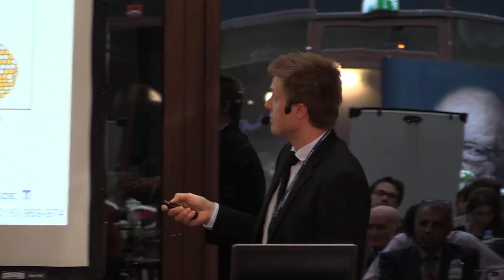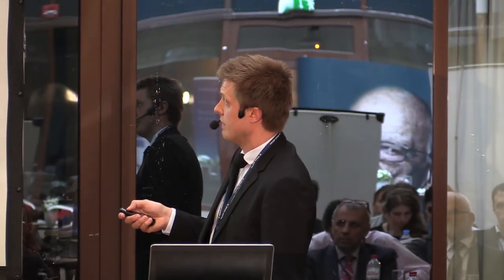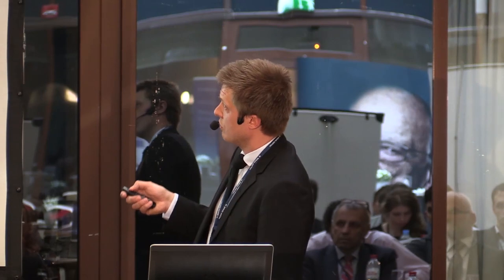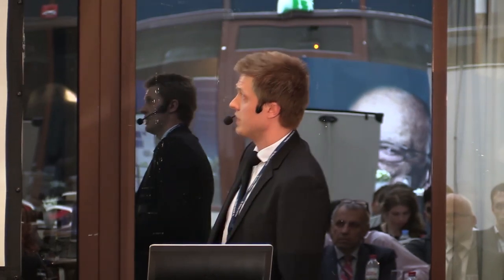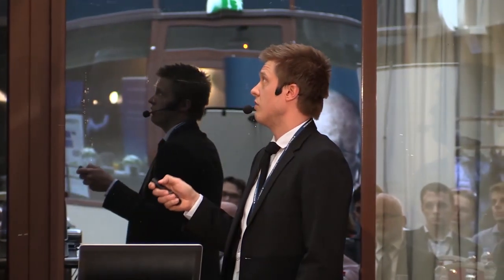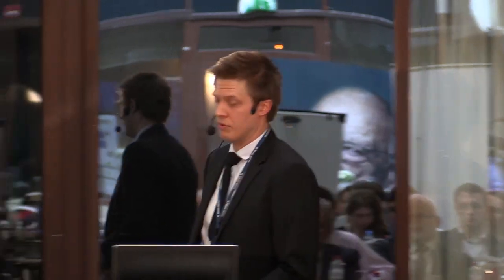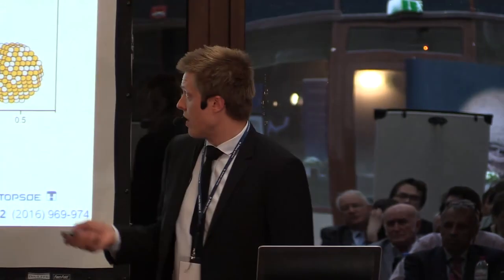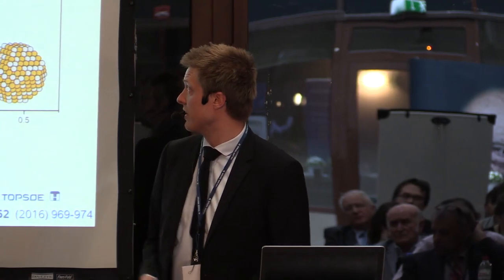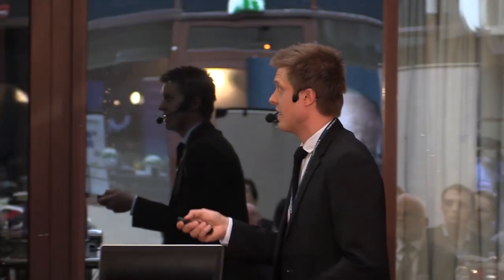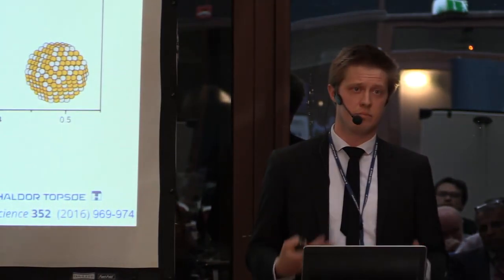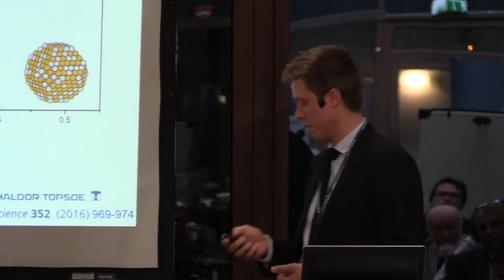And what you can see here is there is a very strong correlation again. For low coverages, it seems to be almost linear, and it seems to level off when you approach half a monolayer. So now we can see that having zinc in the surface of your copper particles is really a key descriptor to understand and improve your methanol activity.